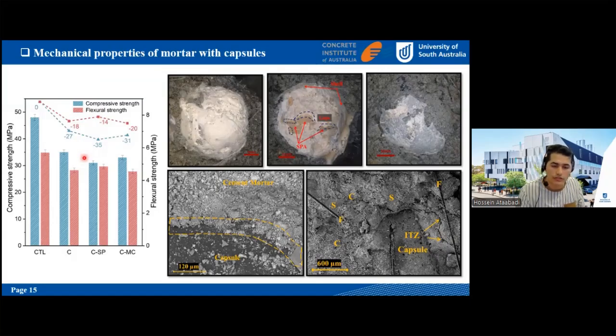So it's usually decreased. This decrease is because the capsule's interaction with the cementitious material is not that strong, because the ethyl cellulose we are using is a kind of hydrophobic material. So the bond between cementitious material and the capsule is not that strong. And also another impact could be that the strength of the granules itself is less than the sand and coarse aggregates. So it reduced the overall strength to some extent.